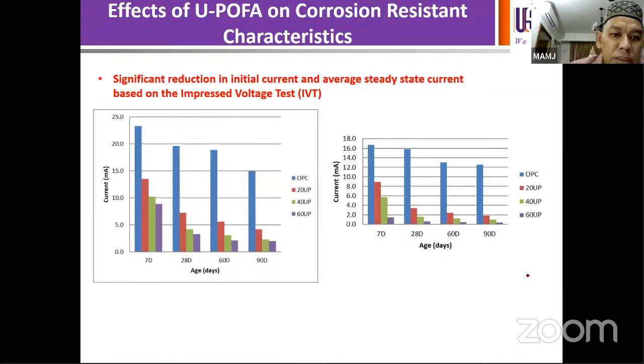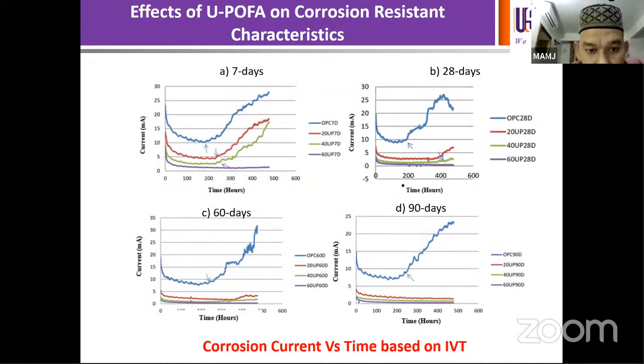All right. So in general, significant reduction in initial current and average steady state current based on the impressed voltage test on the left, as well as steady state current on the right. Okay, especially at a longer curing period of 90 days. All right. Here, corrosion current versus time based on the impressed voltage test. So at 7 days on the left, A, B at 28 days, up to D here 90 days. So meaning that the longer the curing period, the better the resistance of the concrete containing UPOFA, in terms of smaller corrosion current in comparison to the ordinary Portland cement control concrete.